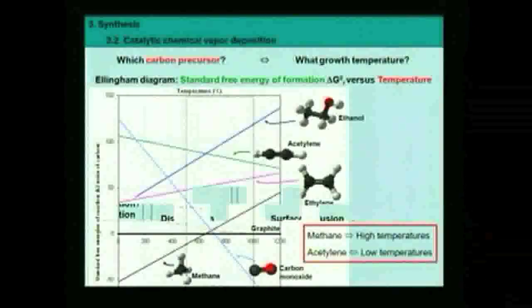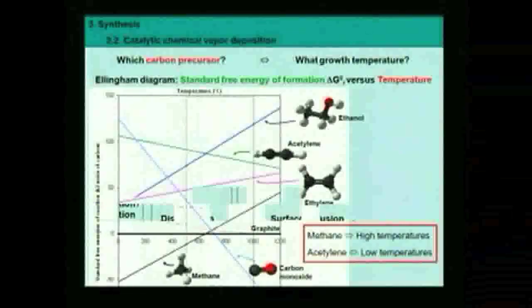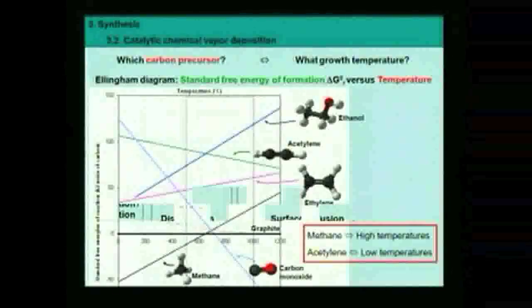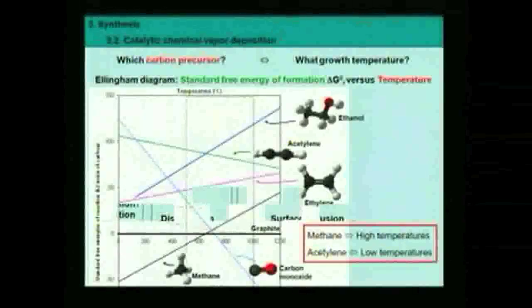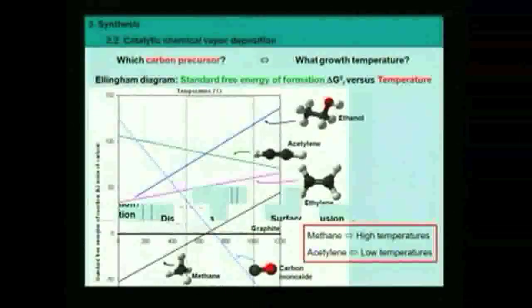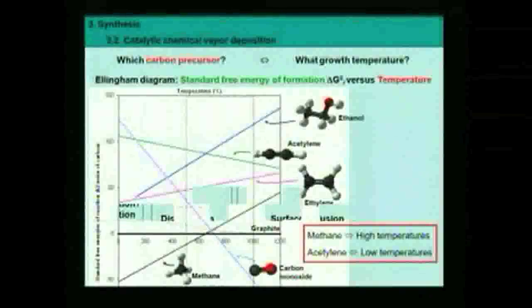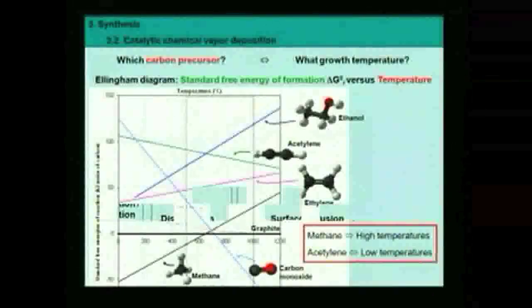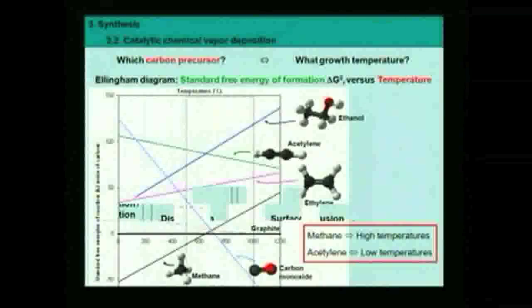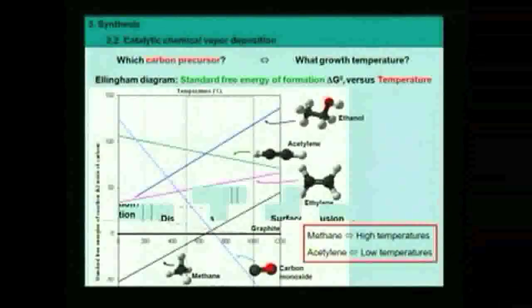It's here. If you use other precursors to make those, you want to know if the reaction is thermodynamically allowed. Being thermodynamically allowed means that you go from a high energy state to a lower energy state. If you look at that, you see that for methane, for instance, its standard free energy of formation is always lower than graphite up to a temperature close to 600-700 degrees C. That means, from this diagram, which is called an Ellingham diagram, a very important tool in thermodynamics, that it is not allowed to make graphite from methane below 600 degrees C.